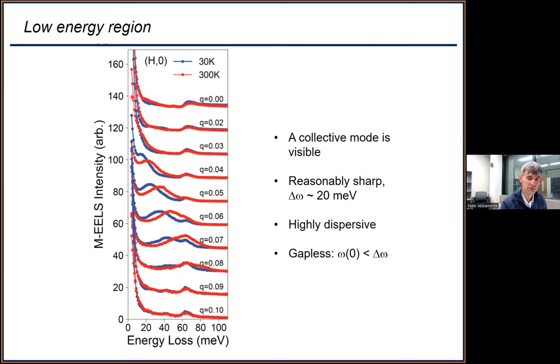If you look at low energy, though, there's another peak there. If I just focus on the red, at zero, it's not there. But as you increase momentum, you can see a peak comes out of the elastic line at zero. And as you increase momentum, it shifts up in energy and broadens, eventually collides with this phonon, and then damps away. So that was the mode that we saw in 2018 and didn't know what it was. It's reasonably sharp, 20 meV or so, depends on Q. It's very dispersive. It's a very fast excitation. And within the precision of the measurement, it seems to be gapless.